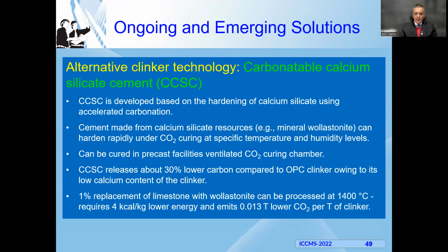The carbonatable calcium silicate cement. Essentially, here we pursue the hardening of calcium silicate using accelerated carbonation. For example, using mineral wollastonite, we can rapidly cure it under CO2 at certain specific temperatures and relative humidities. For instance, in a precast plant, it would be conducive to produce such cement in a chamber that is ventilated using CO2, and which will allow us to reduce maybe somewhere around 30% of carbon emissions compared to ordinary Portland cement production.